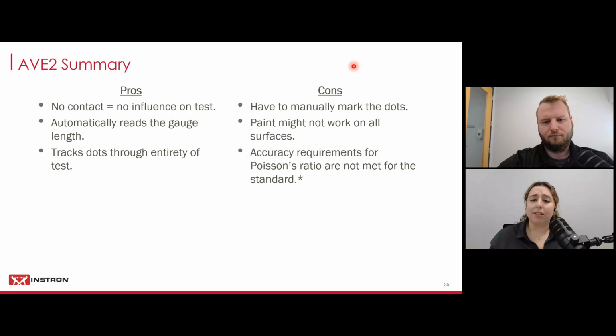And then I just want to go back real quick for the paint. All you want to do is make sure that you have some sort of contrast. So I used white paint. You might need to use black paint. But if your surface is not actually taking that paint and it's not staying on, you might have to get creative and use stickers, or you could draw lines on your specimens. But for the most part, paint pens and dots should work okay.